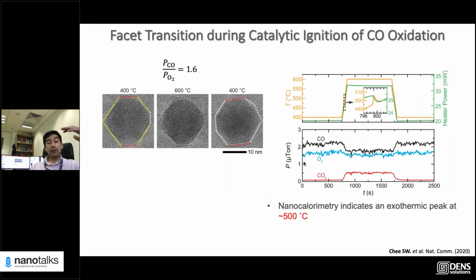Okay, so that was done for the CO to oxygen when the ratio of the partial pressure for the CO and the oxygen was 0.5. Now, what happens if we change that ratio? So if we increase the CO content, you can do exactly the same experiments and monitor what happens. But when you do that, what you see is that this ignition point shifts from 450 to about 500, so your particle becomes catalytically active at a higher temperature.